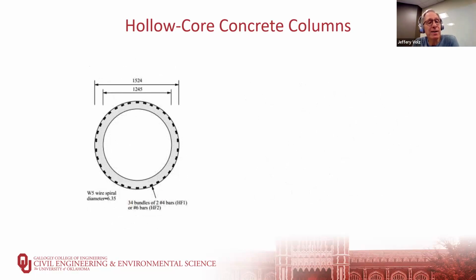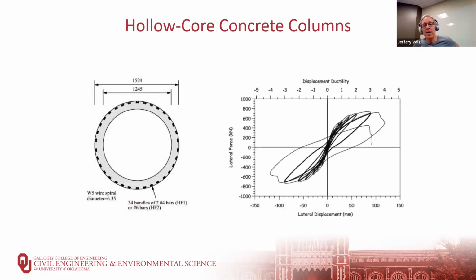And researchers have looked at the opportunity of using round columns, circular columns that are also hollow, with a single layer of longitudinal steel with a spiral around the outside. And then they've tested those in a similar manner under a constant axial load and increasing lateral load. And you can see in this load deflection plot, the ductility is not as good. You can see we get up to a ductility ratio of about 3. After that, we get significant failure of the column.